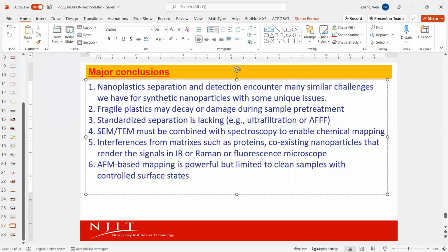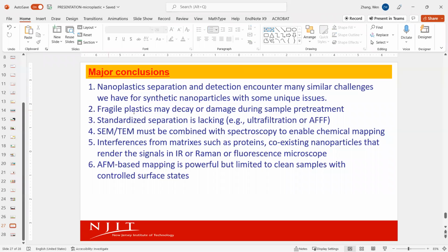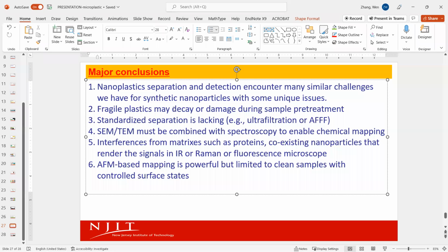I think similar to nanoparticles, we have been facing similar challenges for nanoplastics, especially nanoplastics. I basically overlooked the microplastics since that's not the focus of my talk. And then the plastic particles could decay or be damaged during the sample pre-treatment, even during the sample analysis. If you think about the electron microscope, if some of the polymers are thermally vulnerable or very sensitive, they may melt down at the elevated temperatures, right? Like PE, they may melt down, they may deform or change their phase. So when you perform SEM, TEM, you must be careful.